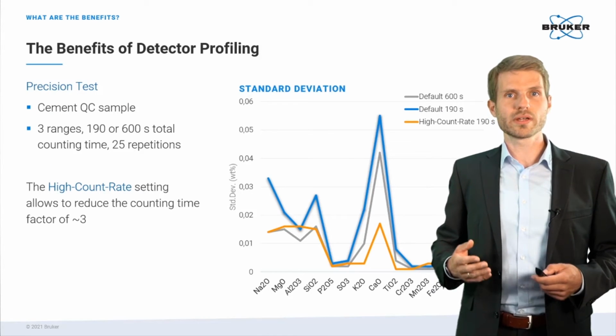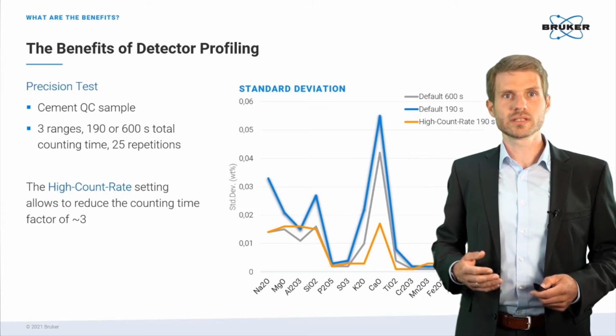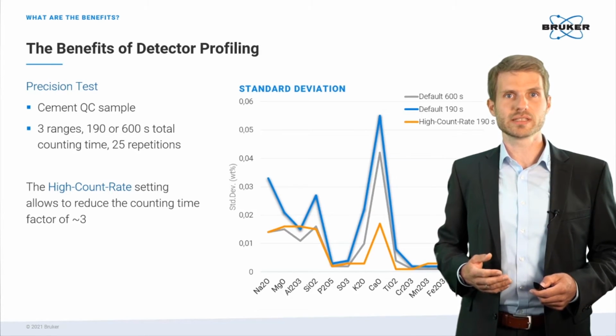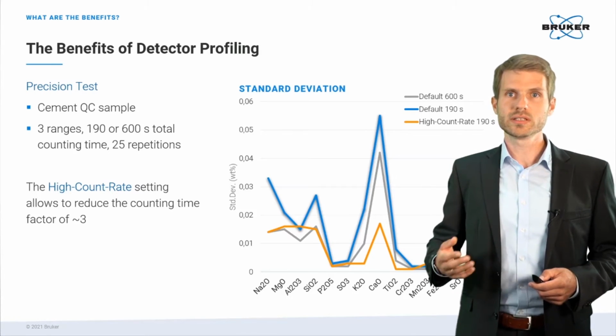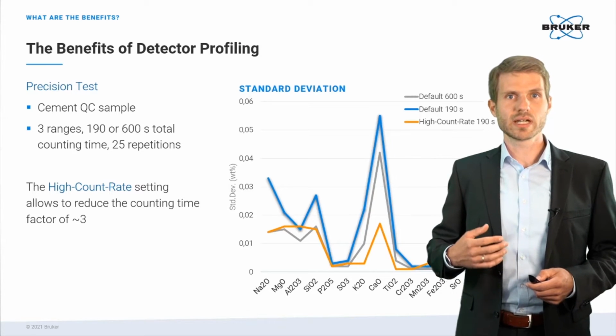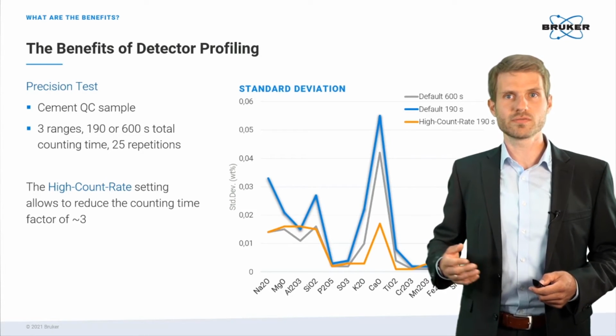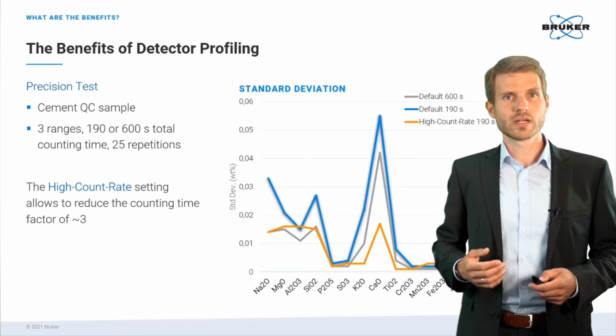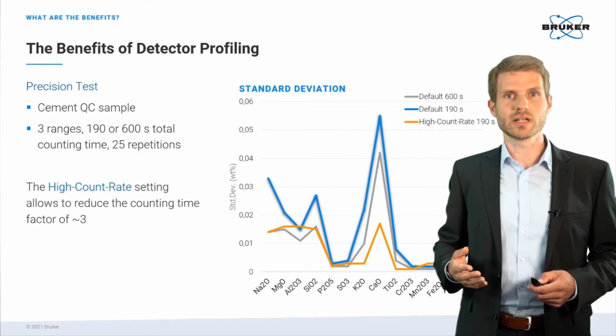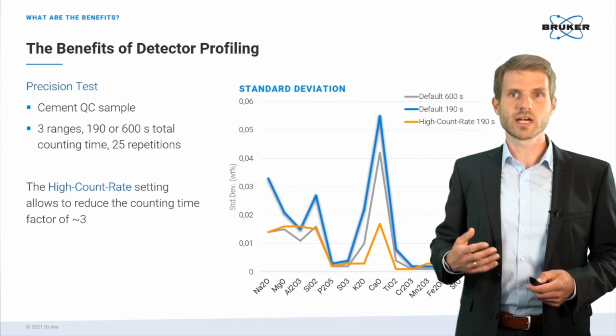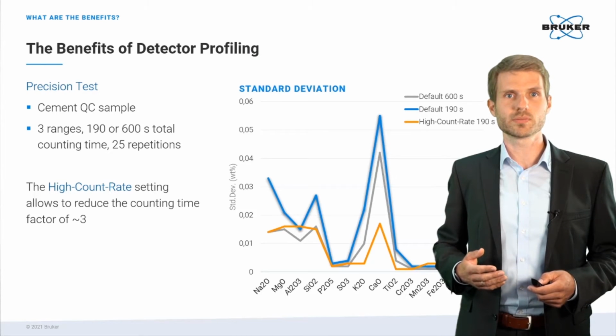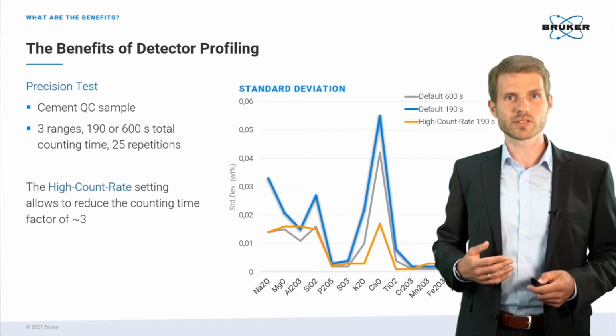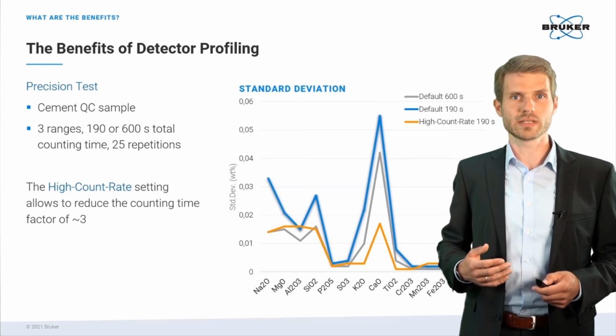To show you the high potential of these features, we performed a precision test with a cement QC sample using different counting times and comparing the high count rate to the default detector profile. The total counting time was 190 seconds or 600 seconds, and we performed 25 repetition measurements. Again, the samples were loaded and unloaded automatically.